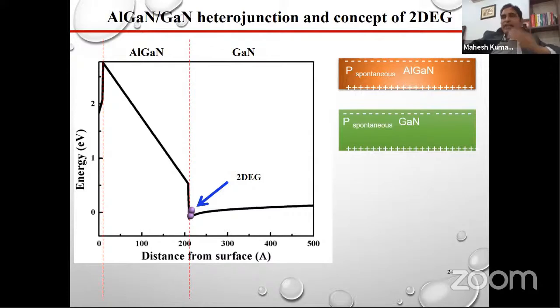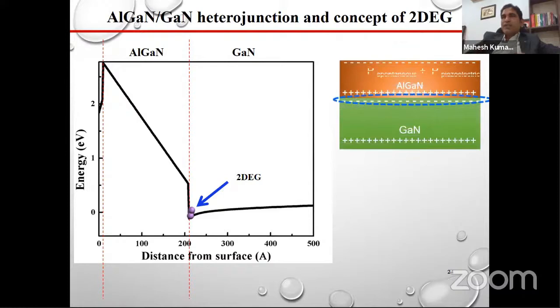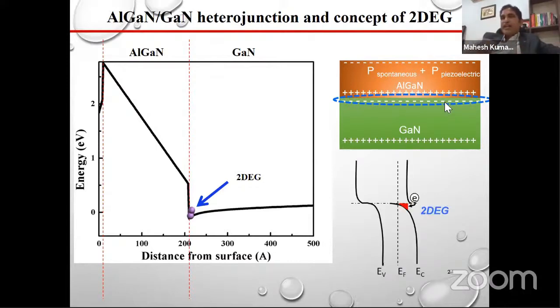Gallium nitride has spontaneous polarization, and aluminum gallium nitride has spontaneous polarization. When we are joining both, because of this spontaneous and piezoelectric polarization, these electrons are trapped at the heterojunction. And if you see the band diagram, this red color is the free electron gas. These electrons cannot move in the gallium nitride, and also cannot move in the aluminum gallium nitride. But at the junction, if we take the contact, they can freely move in the two dimensions.